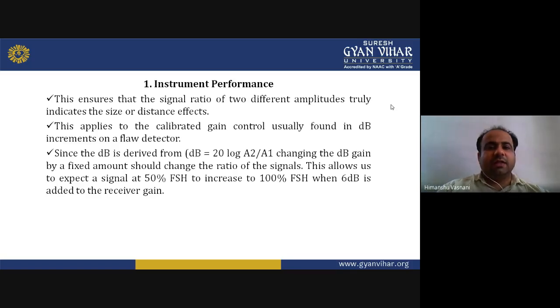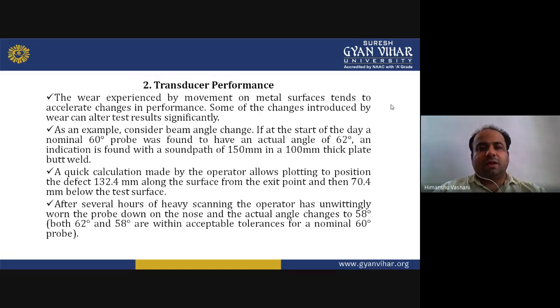This implies the calibrated gain control, usually found in decibel increments on a flaw detector. Since the decibel is derived from dB equals 20 log A2 by A1, changing the dB gain by a fixed amount should change the ratio of the signals. This allows us to expect a signal of 50% FSH to increase to 100% when 6 dB is added to the receiver gain. Now transducer performance.